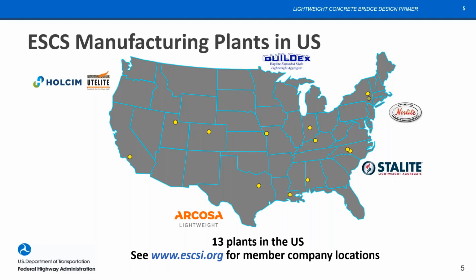And you may think that you're out of luck if your location isn't close to one of those yellow dots on the screen. But just for your information, the project on the first slide, the I-5 over the Skagit River Bridge, actually used material coming from North Carolina, and it was shipped all the way up to Washington State, about 2,800 miles. We don't do that normally with normal weight aggregate, but in this case, it made sense. It could still be competitive to use that lightweight aggregate because of the benefits that the lightweight concrete brings to the table. So just about everybody listening to this is probably closer to a lightweight aggregate source than these folks were.